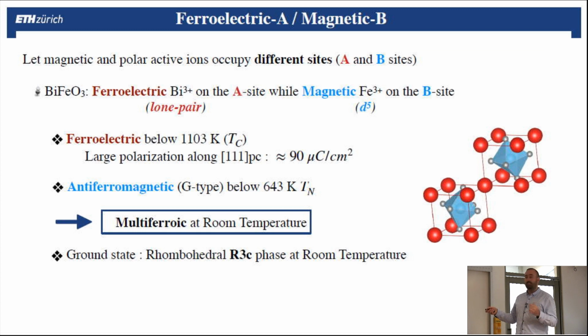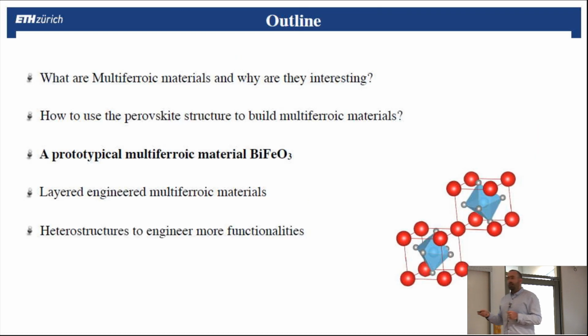And with these two temperatures, what you can notice is that it's actually combining these properties at room temperature, because you can go below this temperature, you are at room temperature, and you would have the two properties. And that's why it's the most studied multiferroic material, because it's the only one that is multiferroic at room temperature. And it has this crystal structure with the polarization along this diagonal here, and the spins would have one type of spin here and the opposite direction for this one.